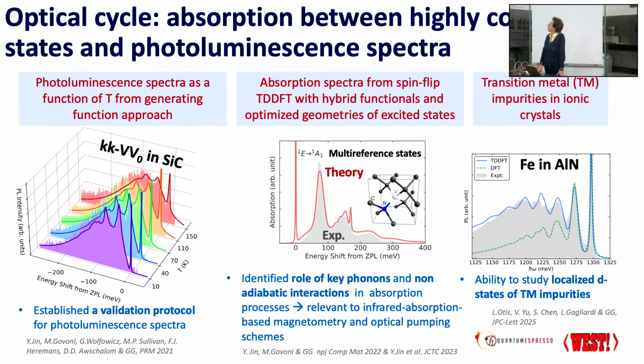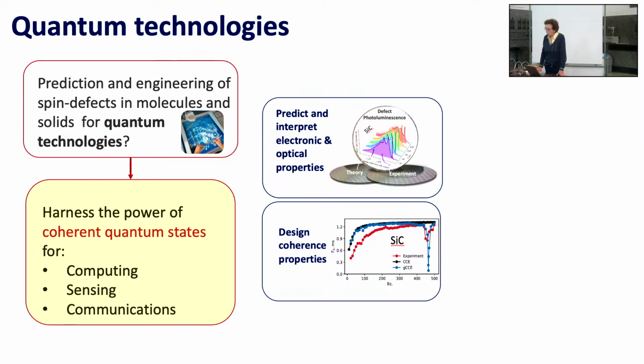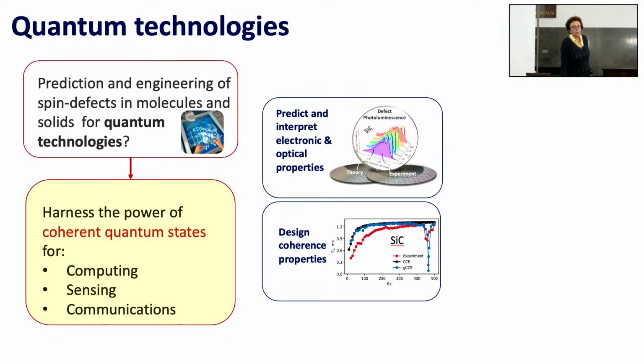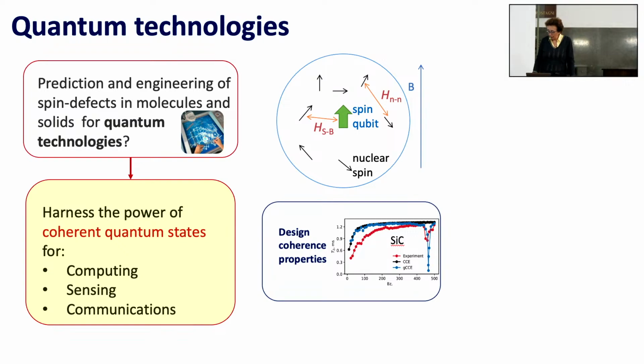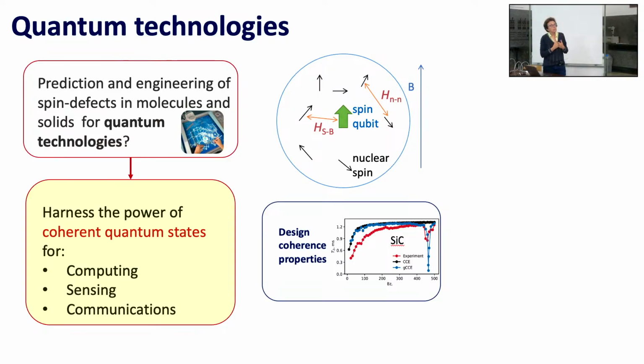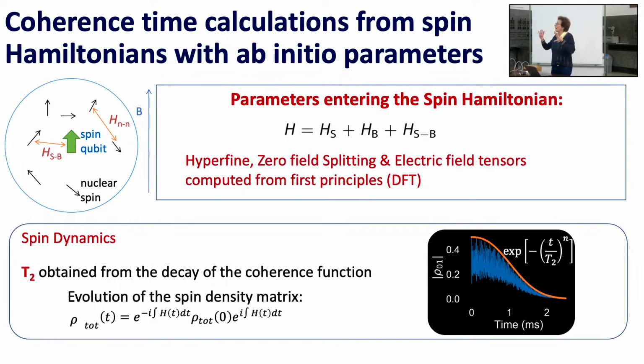So once you have prepared your system with the defect in the coherent state, you want to know how long it stays there, the coherence time. And how long it stays there is determined by your electronic spin interacting with the nuclear spin and other defects. For the interaction of the electronic spin with the nucleus, we use spin Hamiltonians with parameters derived from DFT. This is another very long story, but you set up a spin Hamiltonian, and then you look at the time evolution of the spin Hamiltonian and how long your system takes to decay.